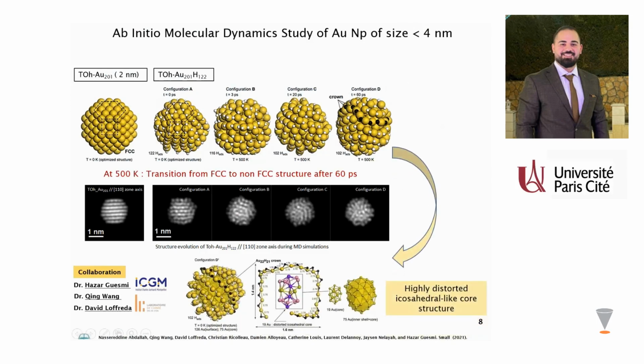Moreover, the optimization by DFT of the structure obtained after 60 picoseconds of molecular dynamics shows the formation of irregular, ordered chains of gold and hydrogen on the entire surface of the particle, leading to a highly distorted icosahedral-like core structure, which is completely consistent with our experimental observation.